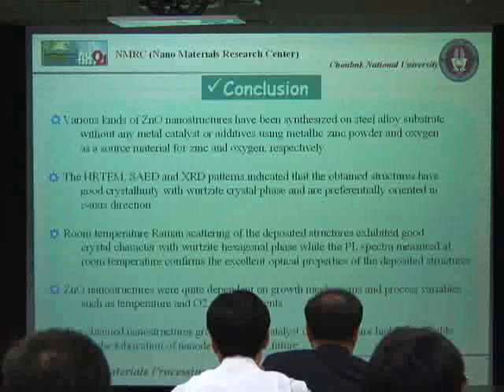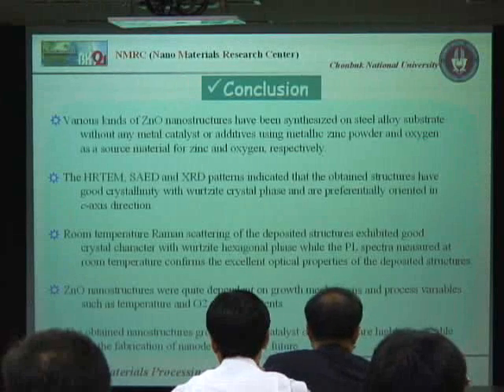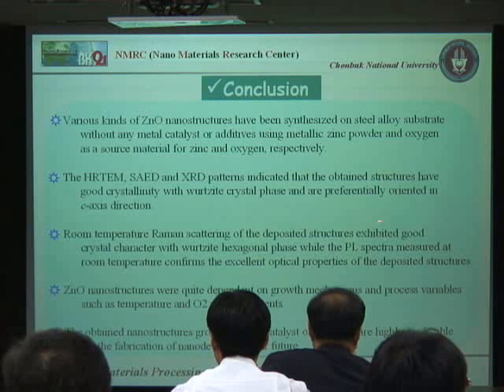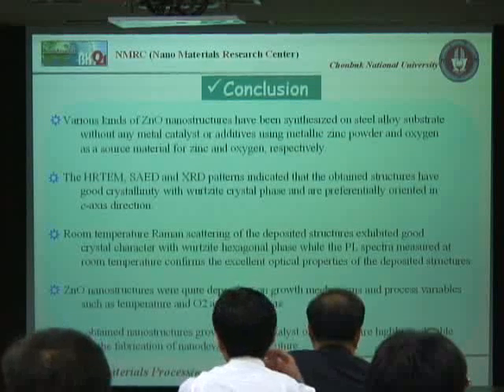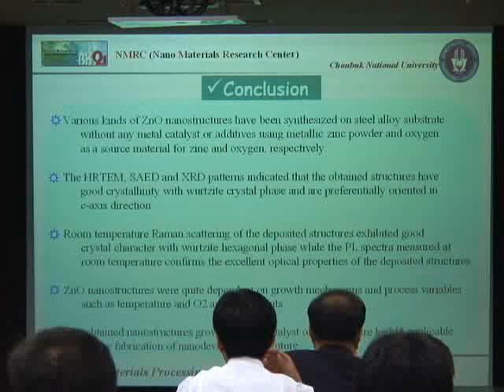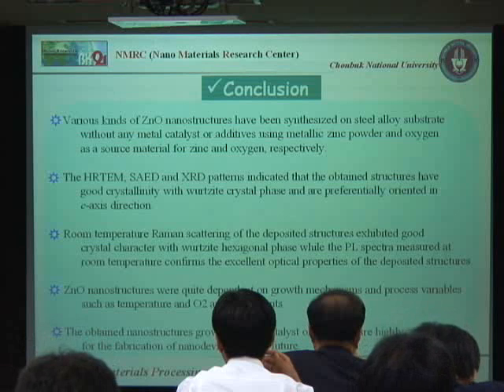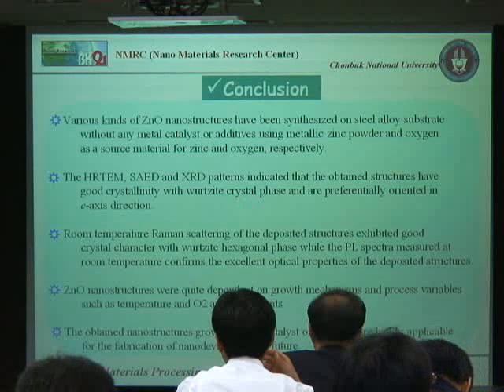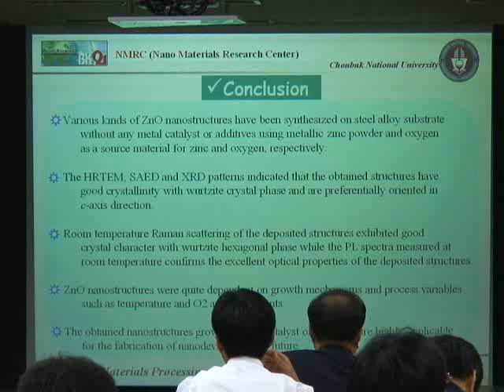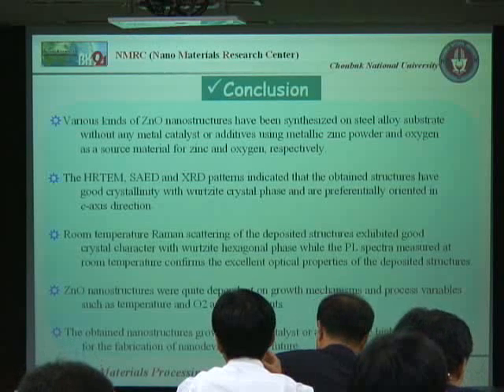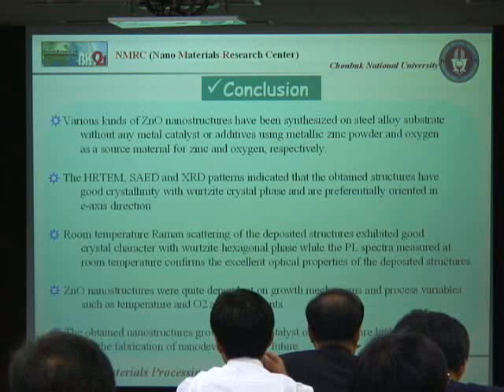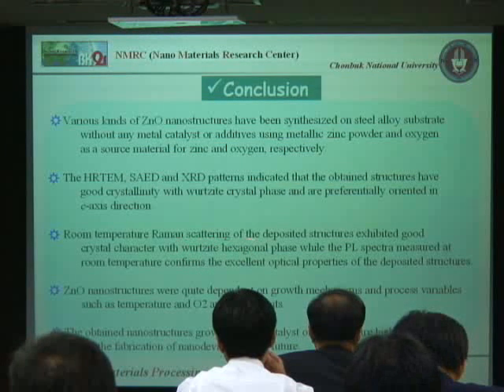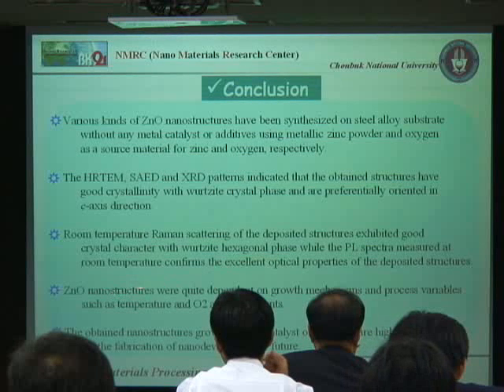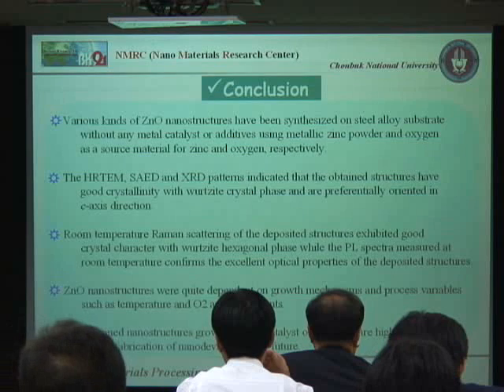So, in conclusion, I would like to say that we grew various zinc oxide nanostructures on the substrate without any help of any catalyst, just using zinc powder and oxygen gas for the source of zinc and oxygen. And the detailed experiment and structure characterization indicated that our grown nanostructures have good crystallinity. And our grown nanostructures are showing excellent optical properties, as I showed in the previous discussion. And also the nanostructures of zinc oxide are quite dependent on the growth process variables such as oxygen and zinc content.